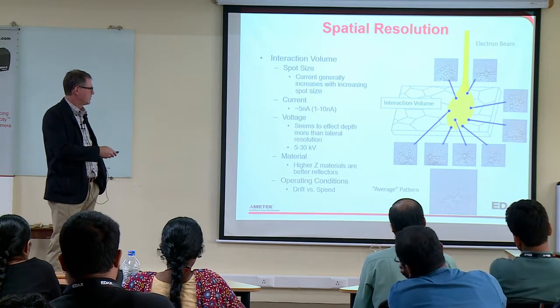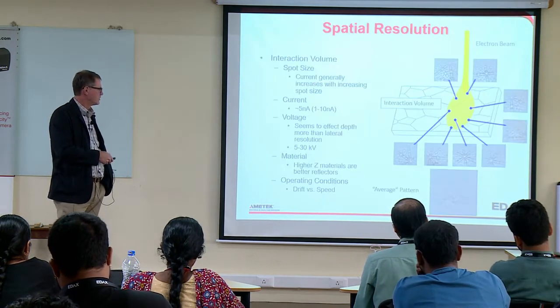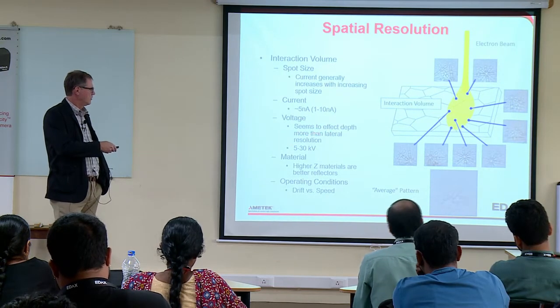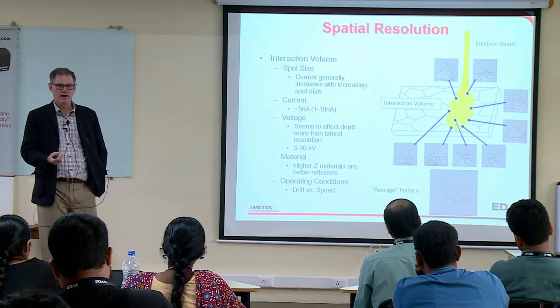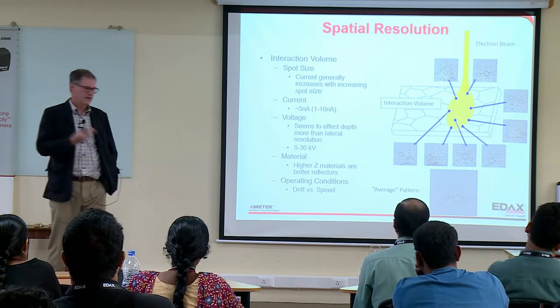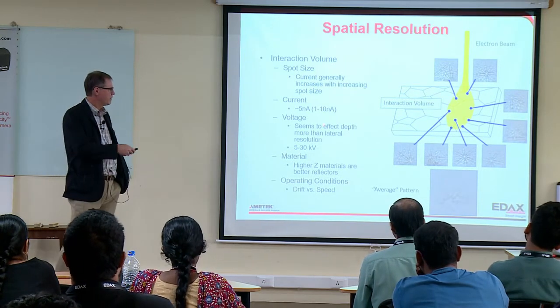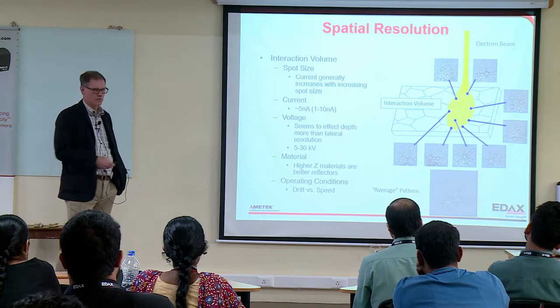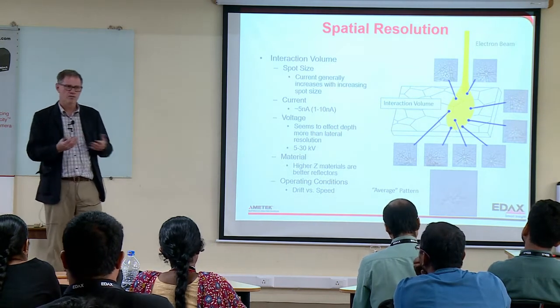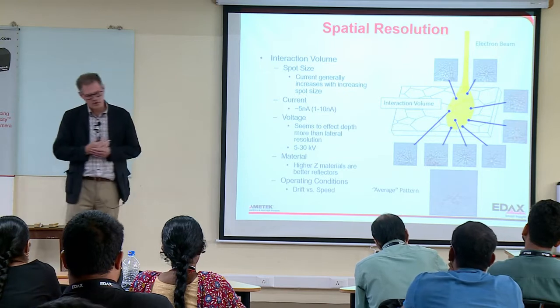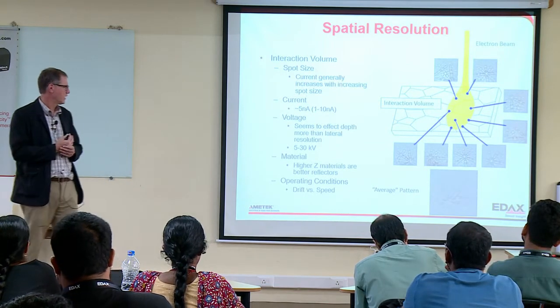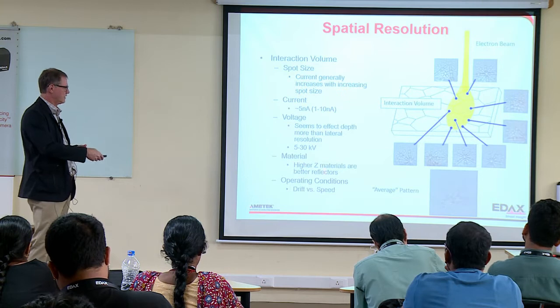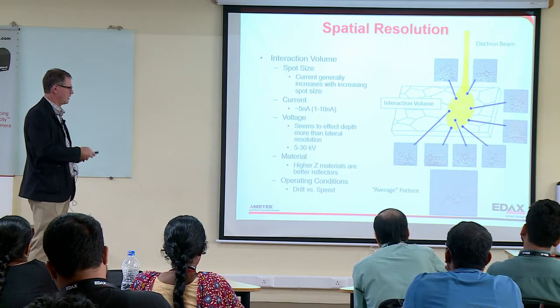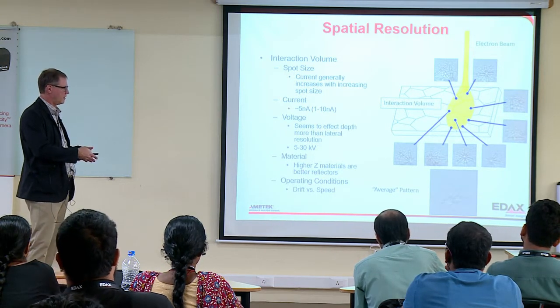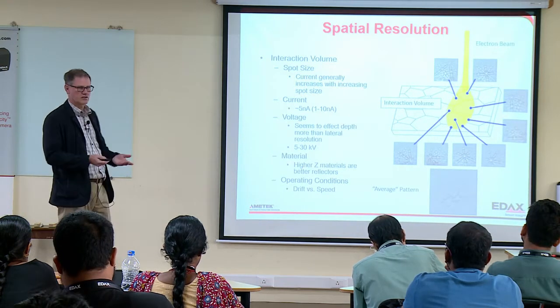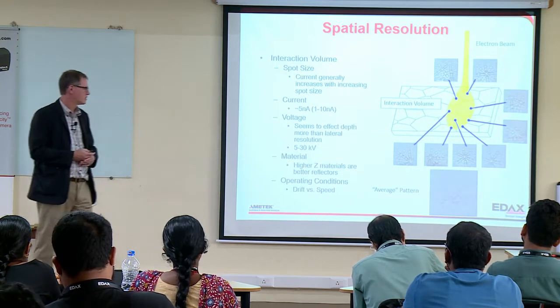The other thing that might affect it is voltage. If you decrease the voltage, you get a smaller interaction volume as well. But there is a limit to that. What we have found is that it seems to affect the depth resolution more than the in-plane resolution of the sample. Not entirely sure why that's the case, but we've observed that. Obviously, your material and its state will affect your resolution. If you've got deformation, it's going to make it harder. Higher Z materials are better reflectors. You'll need less current. You can get better patterns.